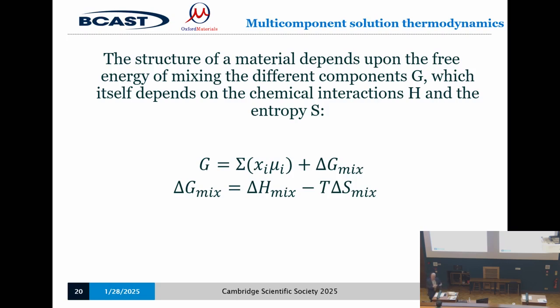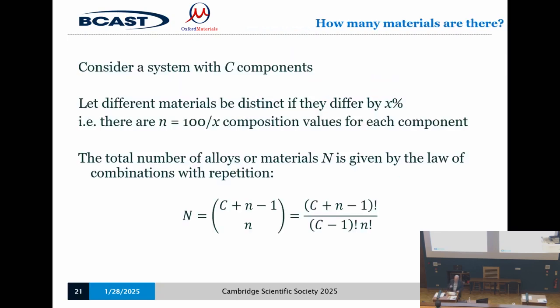Once you get beyond about 5 or 6 components, this term starts to become significant and worth worrying about. That's why you start to develop these random structures, because suddenly the entropy term gets big enough. Not always. If the compound-forming tendency is big enough, you still get compounds, like in our 20-component material. But in many cases, you get this randomizing effect on these crystal structures because of that entropy term. So that's the answer to my first question.